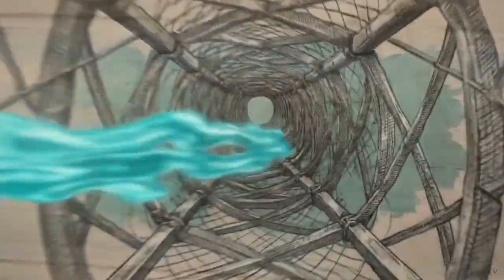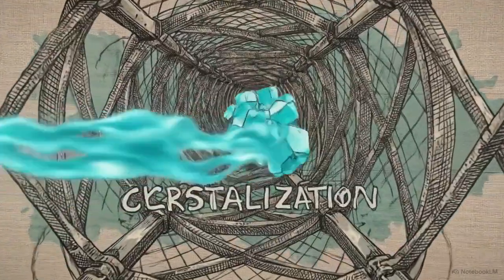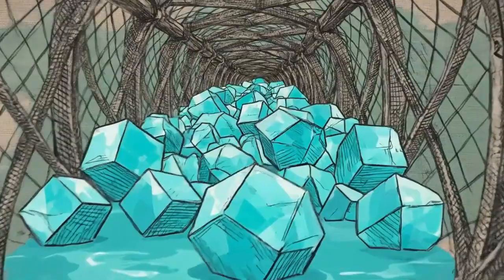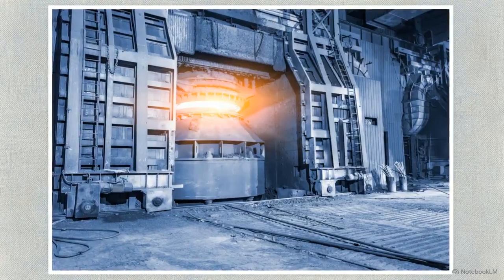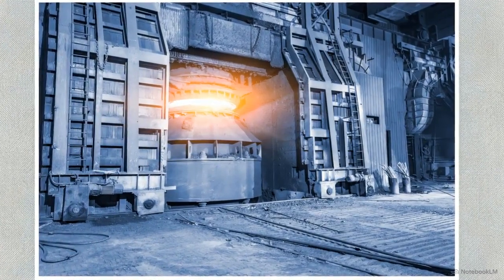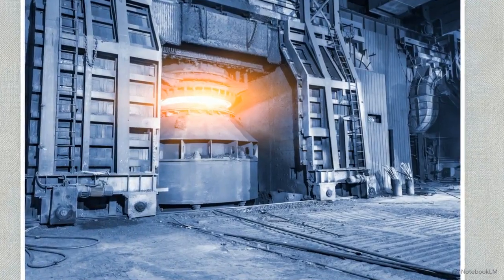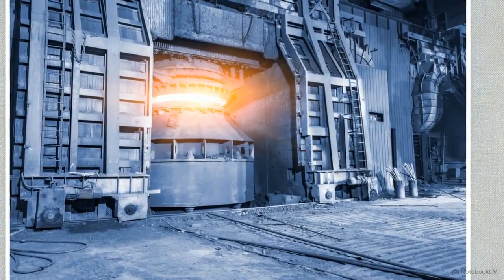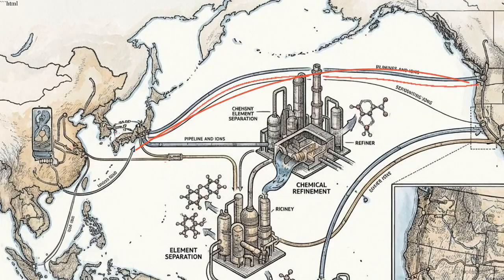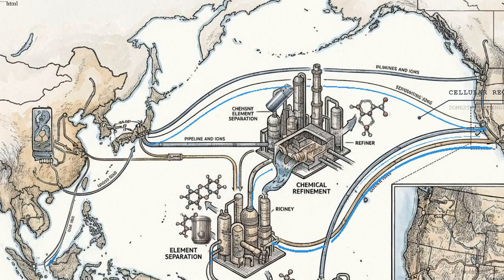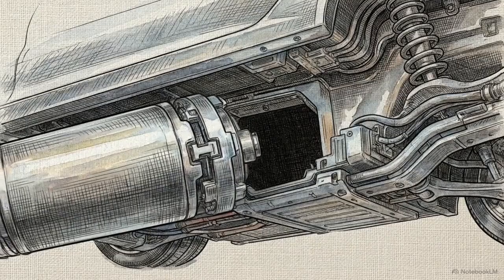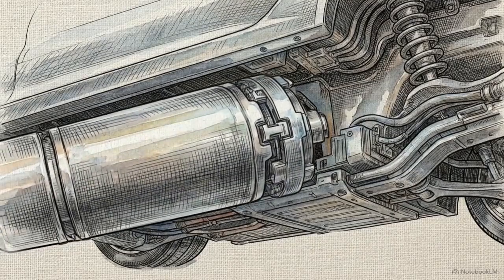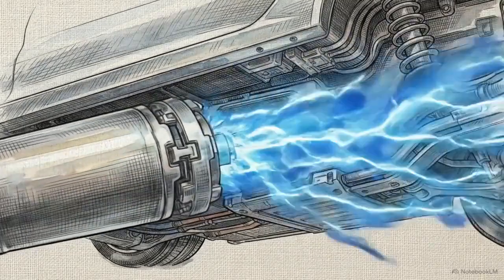Through a highly orchestrated sequence of submerged mechanical neutralization, acidic dissolution, and solvent extraction, we rescue these critical elements from total destruction. By mastering this low-temperature aqueous chemistry, the industry bypasses the massive carbon footprint of traditional smelting and drastically reduces our reliance on vulnerable foreign mining supply chains. A sustainable, electrified future relies on the chemical mastery required to return every gram of recovered metal to the production loop.